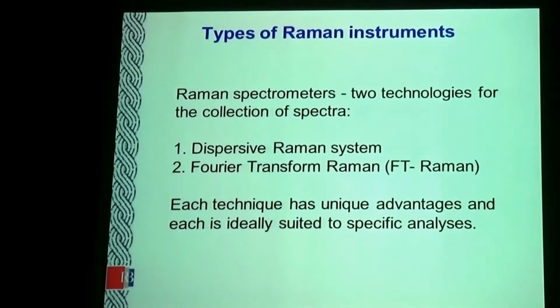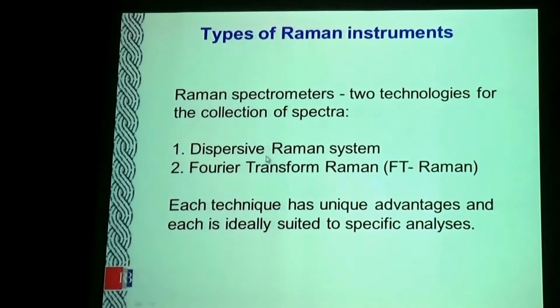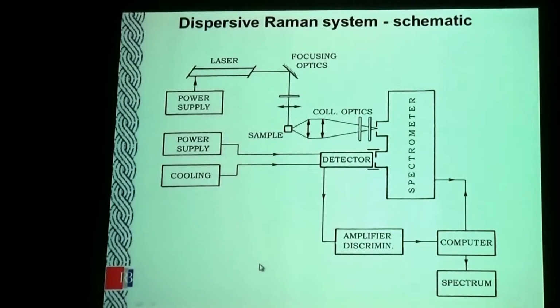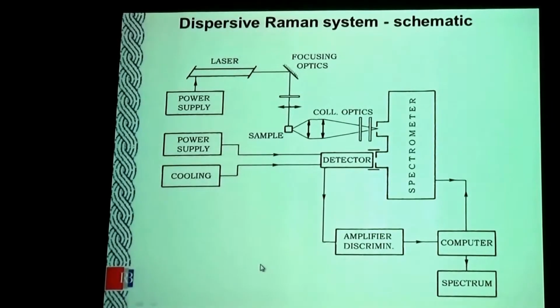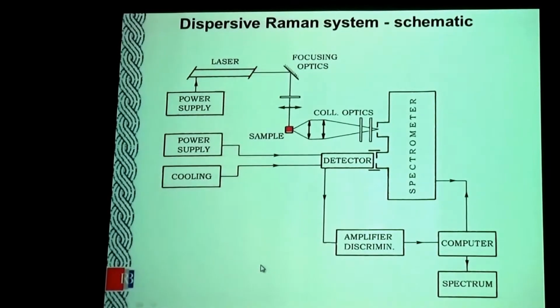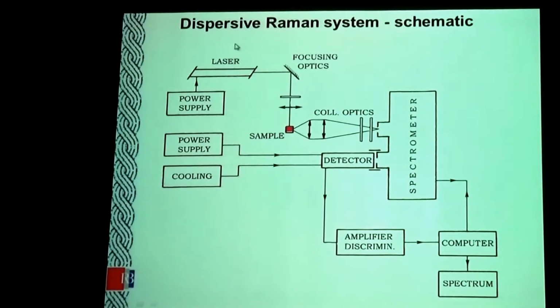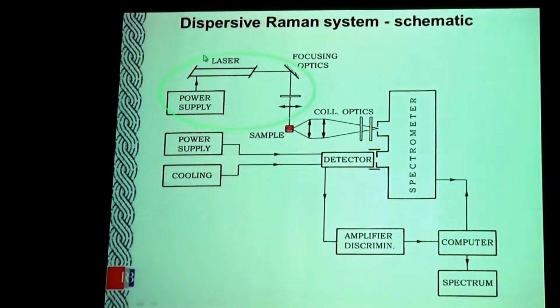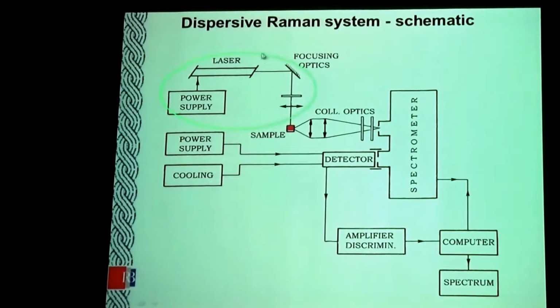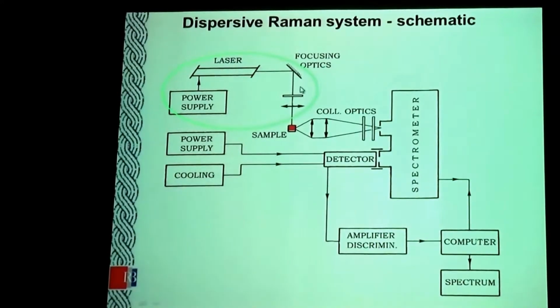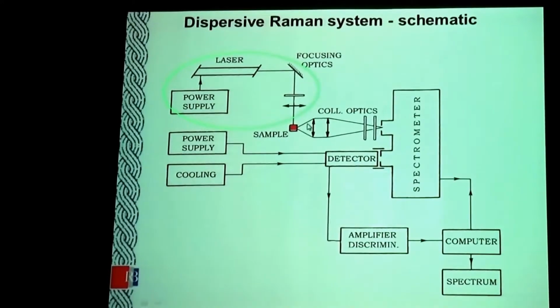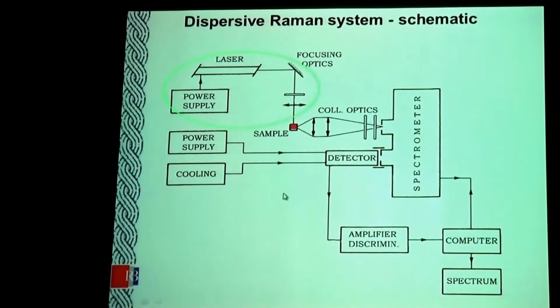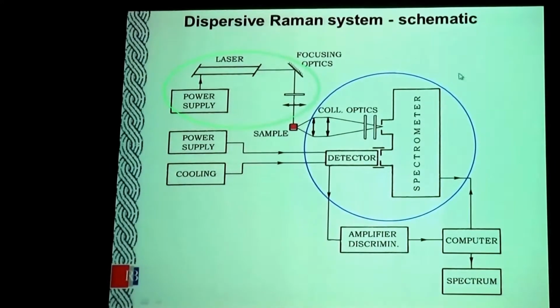Now I will switch to instrumentation. Since I already mentioned, there is dispersive Raman system and Fourier transform Raman system, which have different kinds of physical data. So when we start with a dispersive Raman system, we have sample, we have laser, and we should focus our laser line at the sample to excite the vibrational modes, and we have a spectrometer.